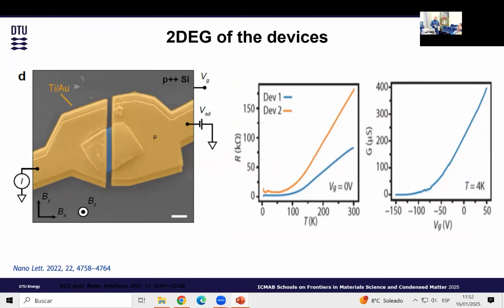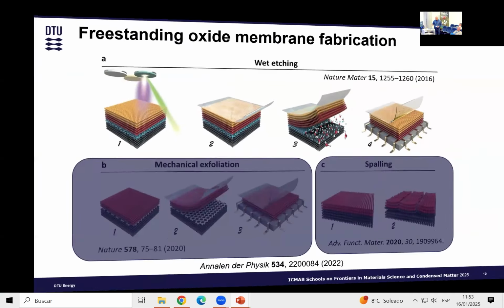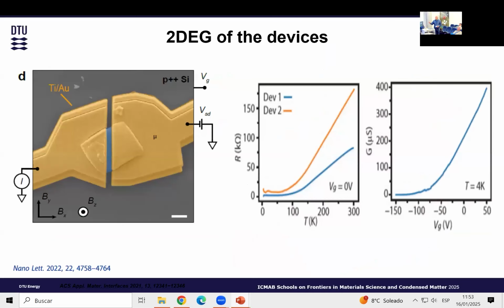What we did, we took one of the samples and made a device out of it. This is a two-terminal device, and we have a backgate here, which is P-type silicon. What we measure, not surprisingly, is metallic conductance, which is what you also expect from LAO-STO. So nothing new about that. When we put the gate on it, we can see that the conductance increases here, and that means that we have negatively charged electrons, so it is an n-type conductor. We know about it. So everything is the same, nothing new about it. The only difference is now we can make it as a flake.